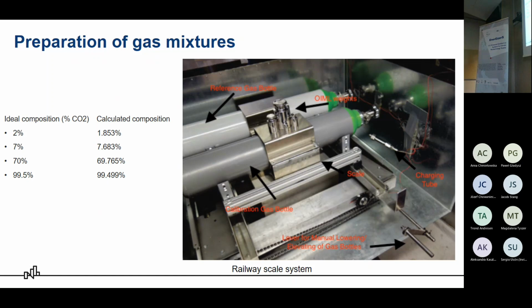We also use the OIML weights to compare the difference in mass, because firstly we add the water into the calibration gas bottle. We measure the mass of the water that we added. We compare it to the reference gas bottle, and the difference between the calibration gas bottle and the reference gas bottle should be as small as possible. So if we added water to the calibration gas bottle, you should also add some mass to the reference gas bottle. So for this case, we use the weights.